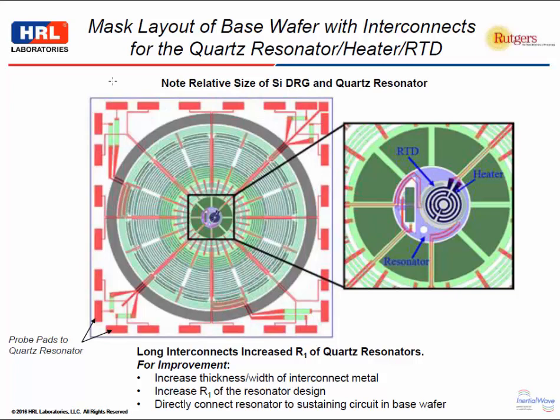It goes in this region, and underneath it there was a heater and an RTD structure for measuring the temperature. And we brought all the interconnects out through these segments here in the base. These segments allow us to get the interconnects in and out, but also when we pump out, eventually we want the silicon DRG and the quartz resonator to be under vacuum. So these served as pump out ports as well to the quartz.